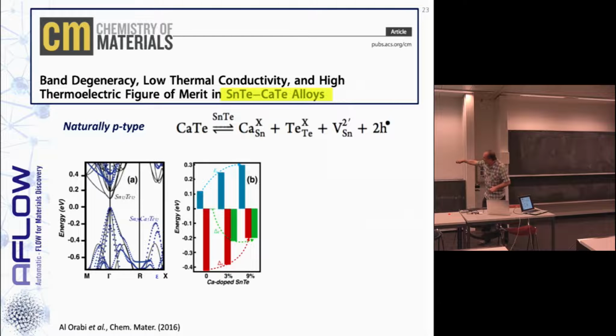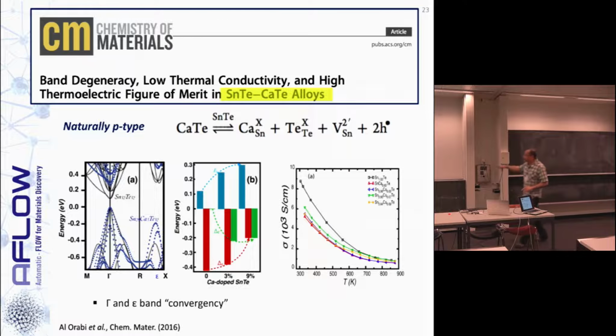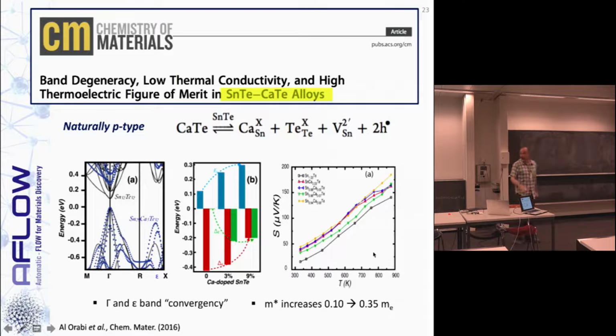So this is the effect, and we searched for all of this, and we found this material particularly promising. So we went to the lab, and these are experimental data. Of course, the addition of calcium lowered the conductivity at lower temperature, because you have a scatter that you don't have otherwise in the pure compound, right? But at higher temperature, it doesn't do much. So this was interesting and promising.